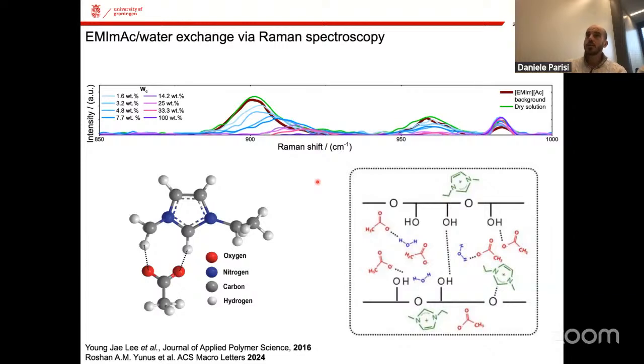So this brought us to, let's say, more atomistic experiments. We measure first the EMImAc, so just the ionic liquid, which is in brown here, and then a dry solution, so in green. Basically, we figure that most of the Raman signal comes from the ionic liquid and not from the cellulose itself. So it's a sort of indirect contrast that we have.